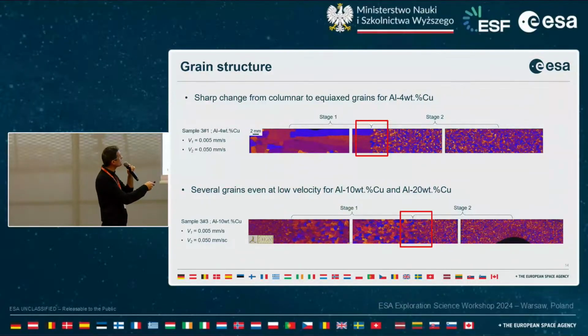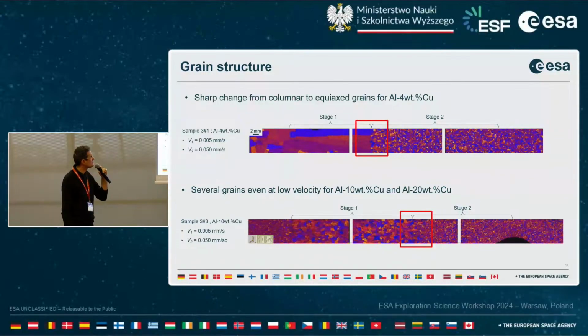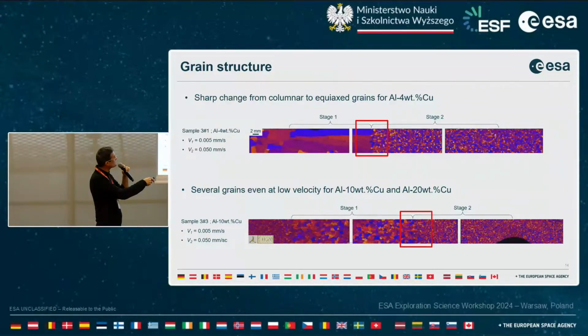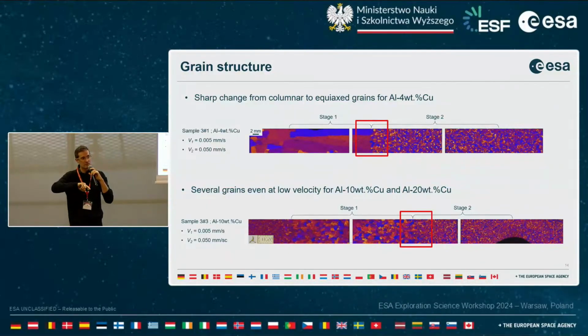So for the 4 weight% copper, you can clearly see the columnar stage where we have nice columnar grains, and after the increase of the growth velocity, we obtain, as expected, a columnar to equiax transition with very small grains. And maybe you can see that grains over here are slightly bigger than grains over here, and this is due to this transient stage, this isotherm velocity that has been increasing progressively, and so the grain size also decreased progressively.